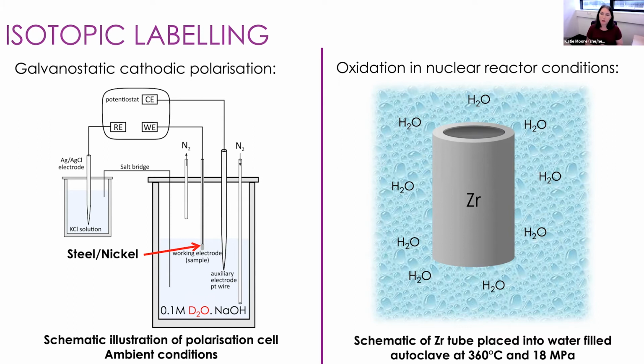So we place the zirconium tube, first of all, into an autoclave containing water with natural levels of deuterium. We allow the oxide layer to grow on the surface to a predefined thickness in most cases, or for a particular time. And then what we do is we take that zirconium tube out of the autoclave, place it into a different autoclave, and this time the water will contain elevated levels of deuterated water or water containing oxygen 18. So those are the approaches that we need to use for this experiment.